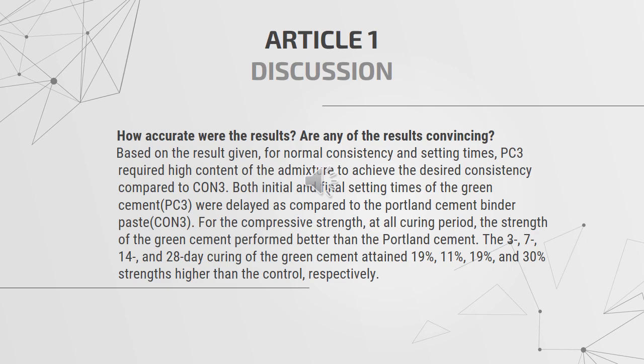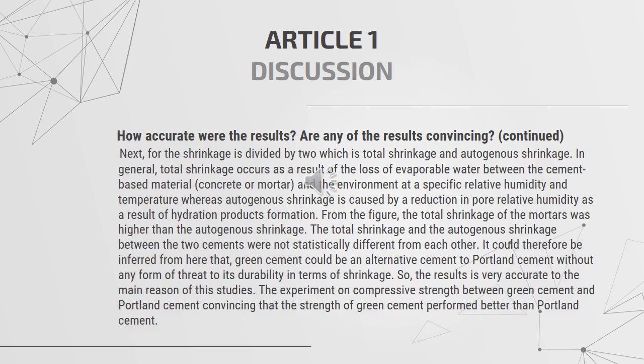For compressive strength, at all curing periods, the strength of the green cement performed better than the Portland cement. At day 3, day 7, day 14, and day 28 of curing, the green cement attained 19%, 11%, 19%, and 30% strength higher than the control respectively. We continue the answer from question 2.